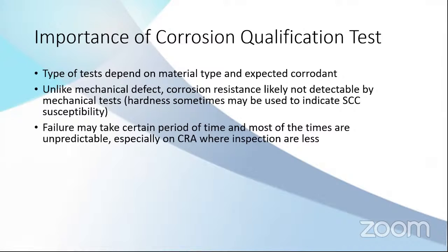And this is also important because you cannot see the corrosion happen right after welding. You need a certain period of time to realize that this weld has a corrosion problem, and this is very problematic with important equipment. Because normally if you make something from stainless steel, let's say, you reduce the inspection frequency because you are quite sure that this equipment will last a lot longer than equipment made of carbon steel. This is the main problem. Many times it failed before you inspected the equipment because you didn't test the corrosion resistance during the PQR.